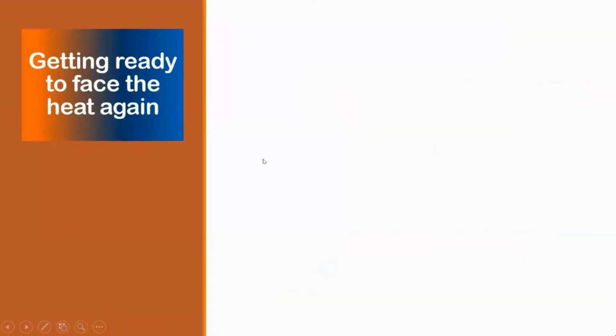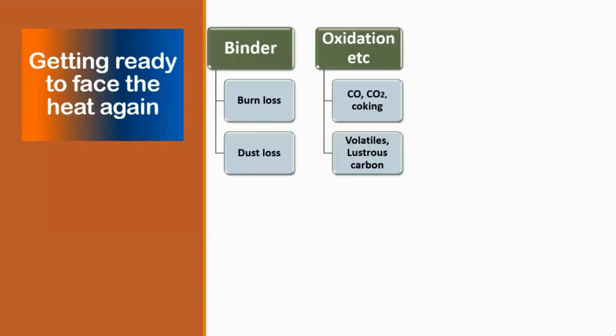So getting ready to face the heat again, which means that you are going to condition this hot sand back to its molding capacity. Let's look at what went wrong due to heat. What happens to the binder? There is a burn loss, which is burnt clay. Then some of it goes as dust while we are extracting the dust at various points in the foundry.